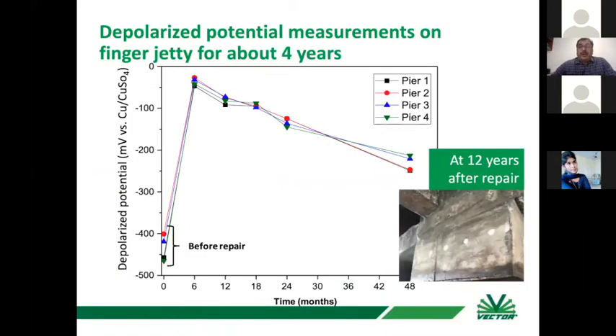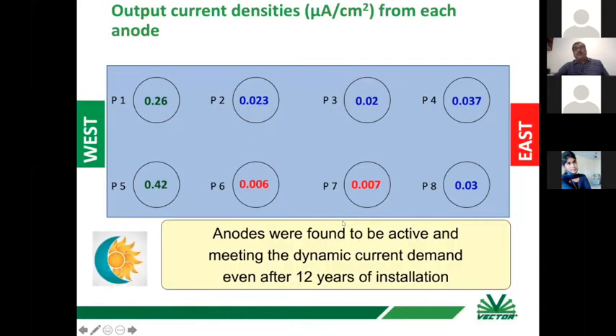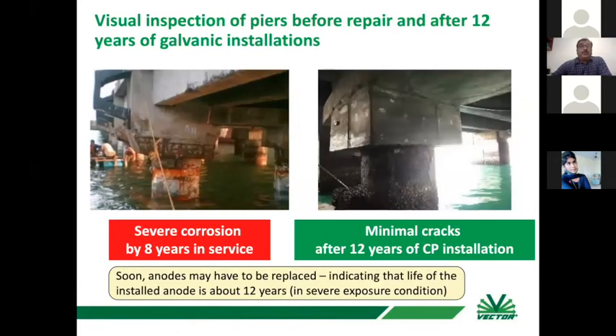Imagine, we had checked there for 4 years as per the contract, and we found that there was depolarization potential of more than 100 millivolts. So it shows that for 4 years anodes were performing, and then anyhow the monitoring was not possible. But after 12 years, we see physically there was no significant damage, and the current was measured. Still, at various 8 locations we are having a good current after 12 years. So the anodes are functioning. If somebody wants, somebody can have a boat and visit the same structure even now also.